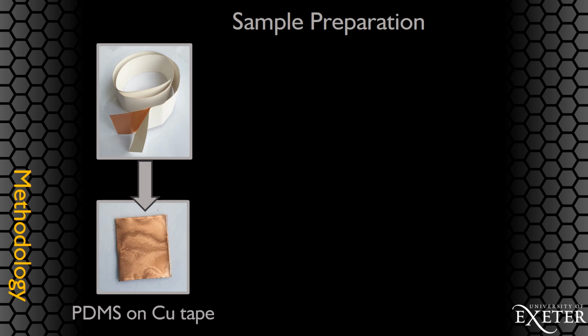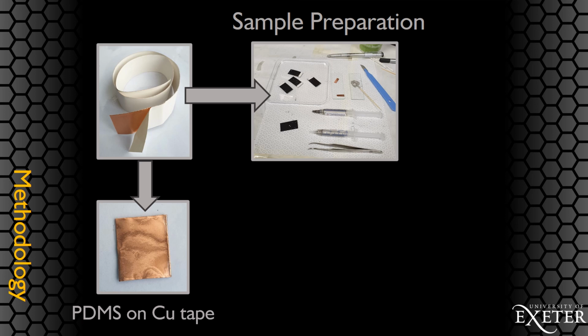Preparing the top PDMS contact is relatively simple and just required drop casting a PDMS solution onto some copper tape, leaving to desiccate and then cutting up as desired. For the bottom PMMA graphene component, they are first cut down to fit on the machine mount. A silver epoxy resin is then smeared on the edge of the device with a small strip of copper tape going on top. This was done to make the contact between the graphene under the PMMA and the rest of